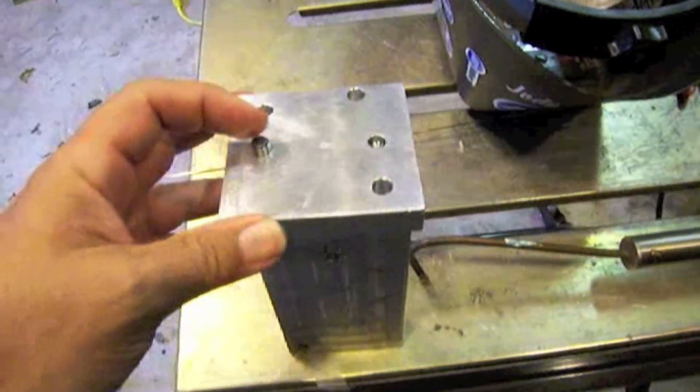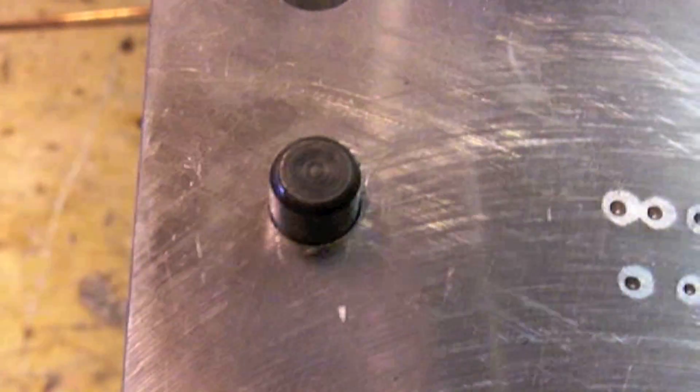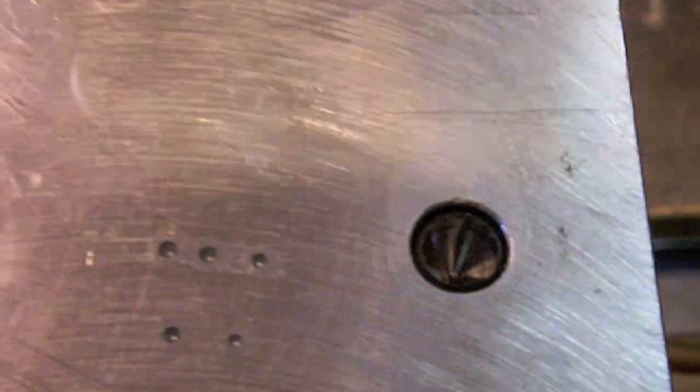Here's the part. You've got one steel pin, it's a line-up dowel pin in there. The other one was mislocated so it needs to be removed. It was attempted to be drilled out and it's down in there about a good three-eighths of an inch with a really thin lip on it around the edge. So what I'm going to have to do is get in there, extend my electrode out way down in there and build up with weld metal so I can get a hold of it with something to pull it out.